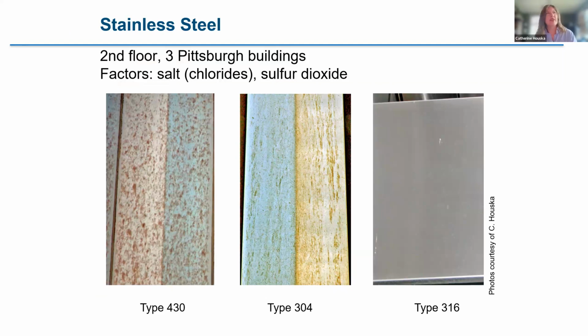I live in Pittsburgh, Pennsylvania. This is the equivalent of the second floor of 3 different buildings. One was 430, another 304, and the final one was 316. And it had been about 3 years since any of these had been cleaned. Being local, I'm often asked for cleaning advice. And that difference in level of corrosion is directly related to the alloy selection. They all had a very fine wet polished number 4 finish. So it wasn't a finish difference.